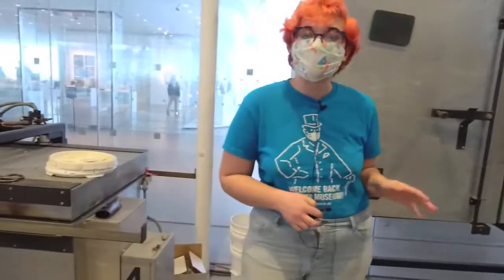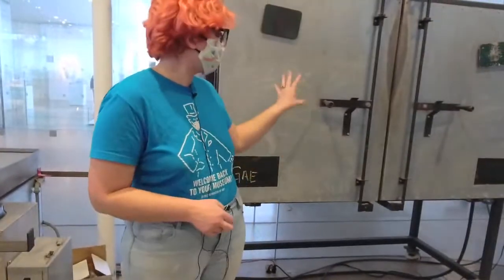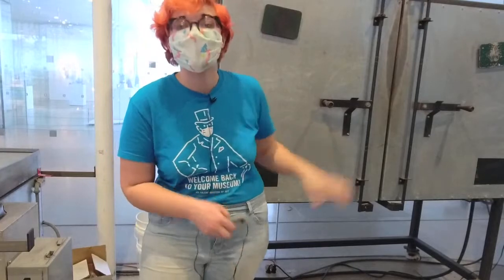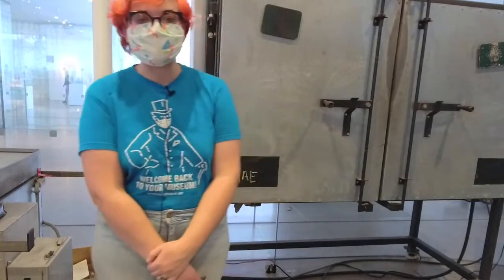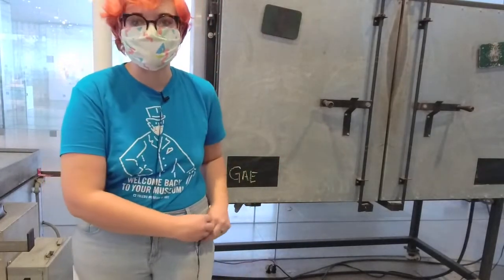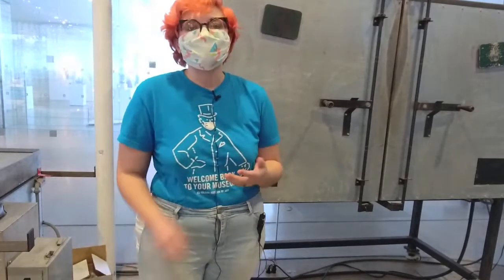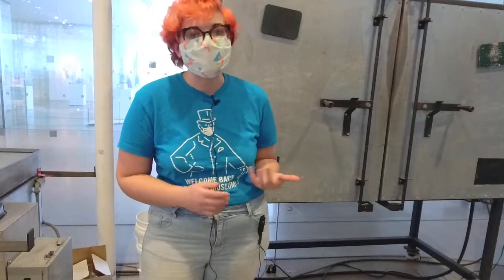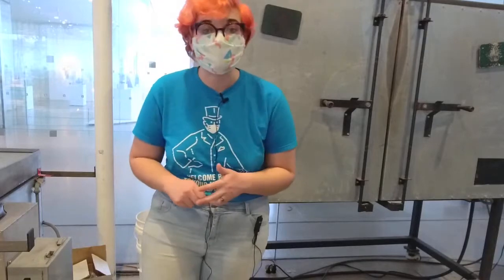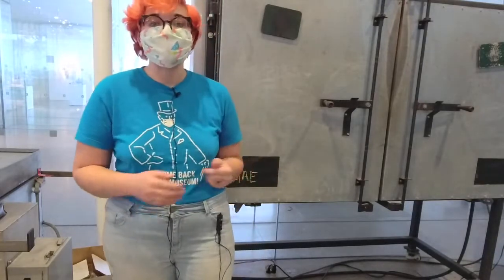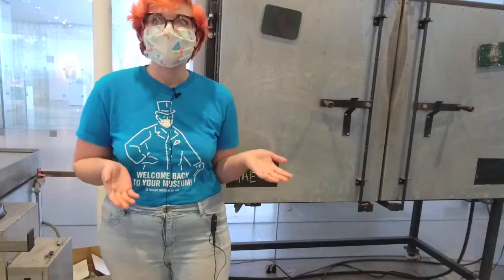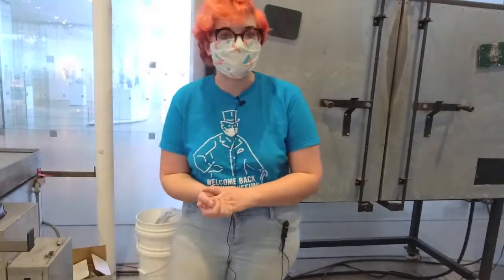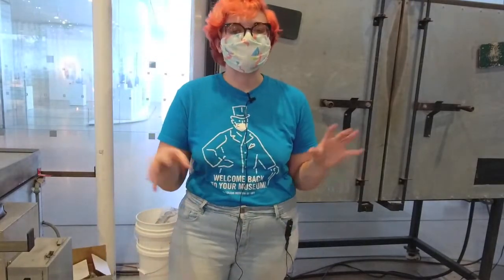Alrighty, so currently where you saw that caterpillar go into is going to be this box right here. So this is called an annealing oven. Annealing is a very slow cool down process. So it's going to go from around 900 to 920 degrees down to room temperature over the process of about 12 to 24 hours. So it's going to cool down super slow.